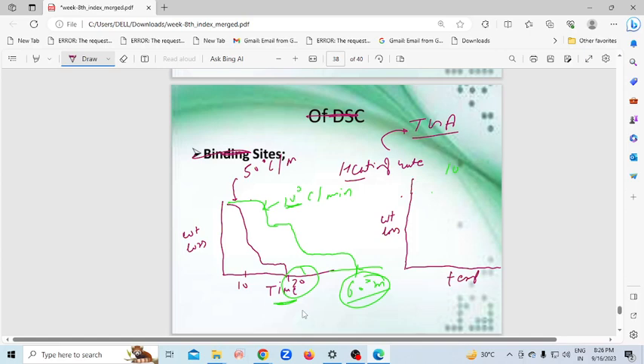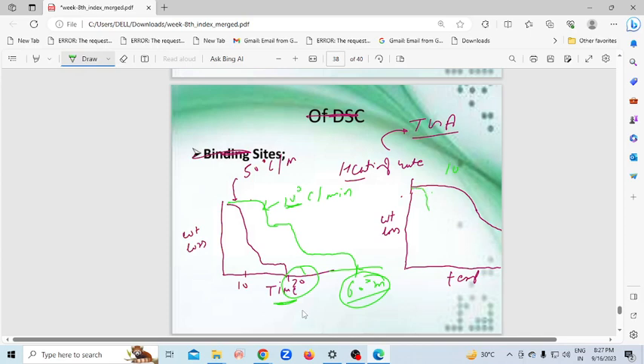Now heating rate is different. First it is 5 degree centigrade per minute. So what will happen, weight loss will occur like that. What is the meaning of that? If your heating rate is higher, weight loss will occur at higher temperature. But if it is low, then I need to change the color. So what will happen, weight loss will occur like that. Suppose this is 10 degree per minute.